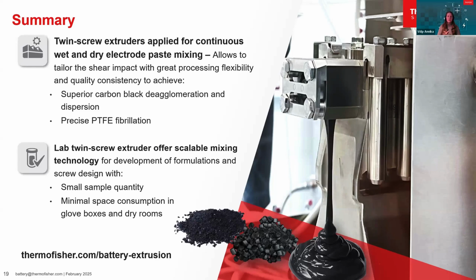In manufacturing, twin-screw extruders allow for the modification of shear effects by adjusting the screw design and processing parameters such as screw speed, temperature, and material throughput. When applied for continuous wet and dry electrode paste mixing, they provide great processing flexibility and quality consistency to achieve a superior carbon black deagglomeration and dispersion and good PTFE fibrillation and binder distribution.